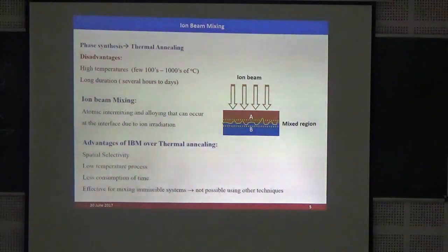So it is a relatively low temperature process, so one can have this ion mixing at room temperature itself. And we don't have to use it for days; at maximum 3 to 4 hours, if your current is sufficient, then at max 4 hours one can get this ion mixing done. And it is also effective for mixing immiscible systems, which is not possible using conventional techniques.